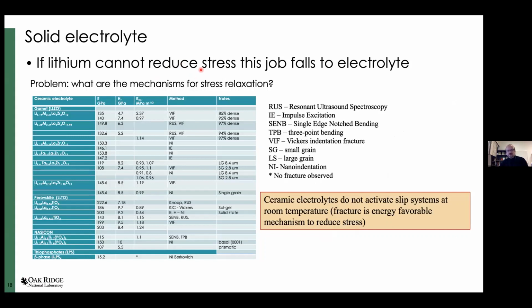Okay, so if lithium cannot reduce the stress, if you get the defect size just right to build it up, this job falls to the electrolyte. And here we encounter a huge problem because there are not so many mechanisms in ceramics to reduce the stress. The ceramic electrolytes hardly activate any slip systems, at least not at room temperature, and they would rather fracture than make dislocations. It's very, very hard to introduce dislocations in ceramics. So fracture for them is energetically a more preferable mechanism.